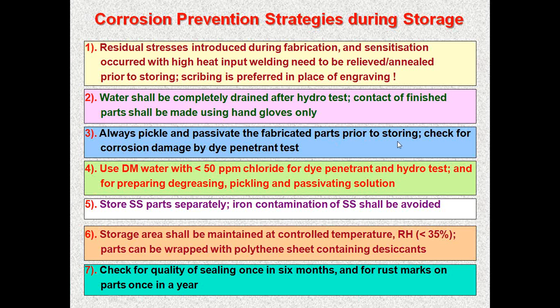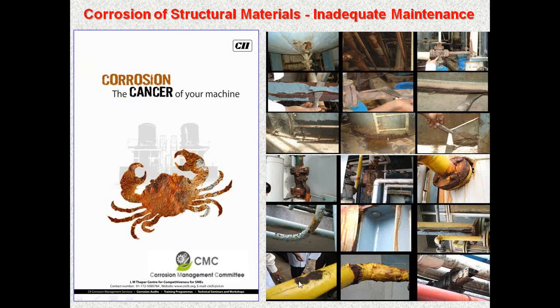Always pickle and passivate fabricated parts prior to storing or prior to commissioning. Check for corrosion damage by dye penetrant test. If it is stored for a longer time, you should check for corrosion attack. You have to use DM water with less than 50 ppm chloride for dye penetrant testing, hydro test, and for preparing degreasing, pickling and passivating solutions. Store SS parts separately. Iron contaminated stainless steel shall be avoided. The storage area should be maintained. Check the quality of sealing once in 6 months.